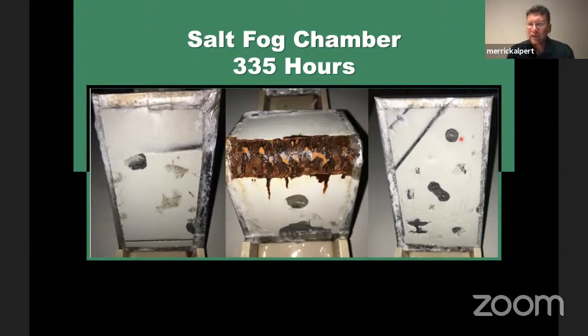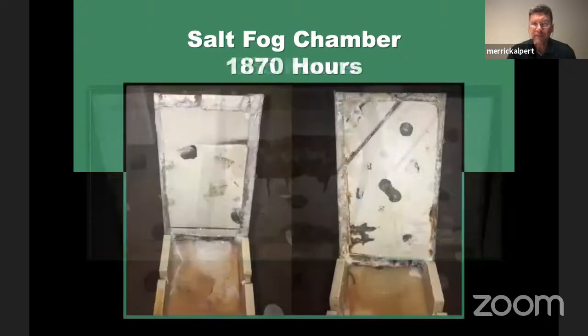Now look at these other areas. If you didn't know it was Eon Coat, you'd think to yourself, how's that happening? How could you have carbon steel in salt water for weeks and have it not corrode? But of course, you now know that you're not actually looking at carbon steel. You're looking at that thin passivation layer. So even when that outer ceramic layer has been torn away, you still have the protection of that passivation layer.